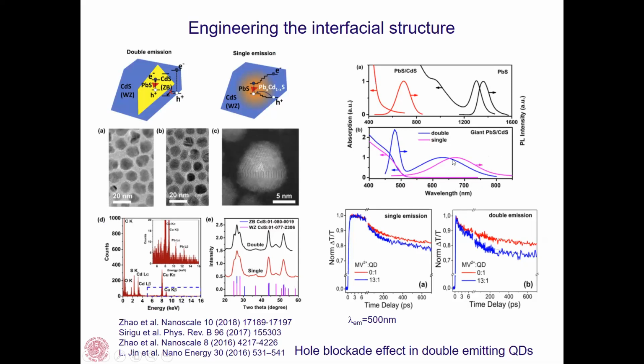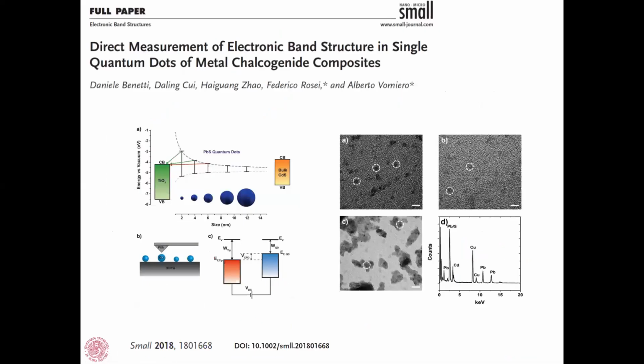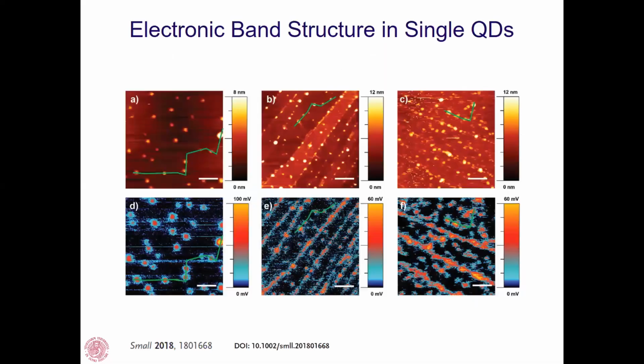You see in the right panel, the second one, the blue and pink photoluminescence. You see the double emission for the sharp interface, and for the graded interface you see a single emission in the near infrared, close to 680 nanometers, testifying that you are really able to tune the optical properties of these materials. And then we also tried to apply Kelvin probe microscopy to investigate the variation of the electronic structure of these materials as a function of the size and of the composition.